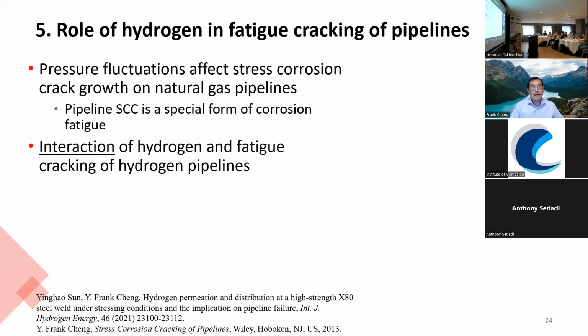Okay, when we use the steel pipeline to carry gas, such as natural gas, our knowledge has told us the natural gas usually experiences pressure fluctuation. So it will influence the stress corrosion cracking very much. So that's why some people regard hydrogen stress corrosion cracking, pipeline stress corrosion cracking, as a special form of corrosion fatigue, because pressure fluctuation induces a certain cyclical stress to cause cracking and propagation.